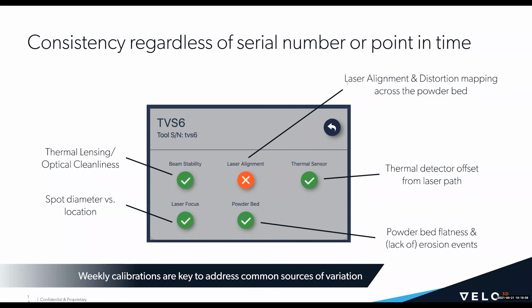Next, we have laser alignment. So we're doing laser distortion mapping on each galvo. And then we also map the two lasers to each other at 500 different points across the build plane and basically ensure that the laser spots are coincident with each other. Next, we calibrate the thermal sensor offset to ensure that we're getting a strong heat signal, or thermal signal, from the melt pool. And then finally, we have some really unique capabilities relative to the powder bed verification.